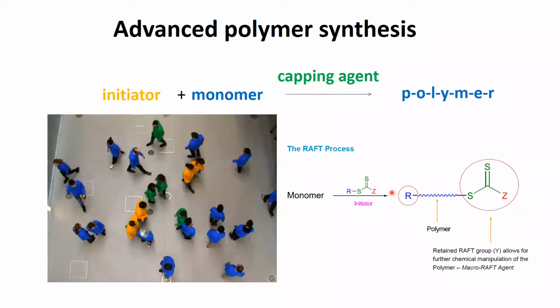There was a big advance, about 25 years ago, that really made a huge difference in polymer synthesis, where rather than just reacting an initiator and a monomer together, you have some sort of capping agent, and this is the chemistry that my group specializes in. This capping agent provides polymerization control and allows you to control the number of monomers added. So you're starting to be able to make polymers that are better defined, with more control, and start to become higher value. This is the chemistry that we use, where we add in a little bit of this compound here, which we call a chain transfer agent, and that essentially controls the polymerization. And I've got a video to try and show that.